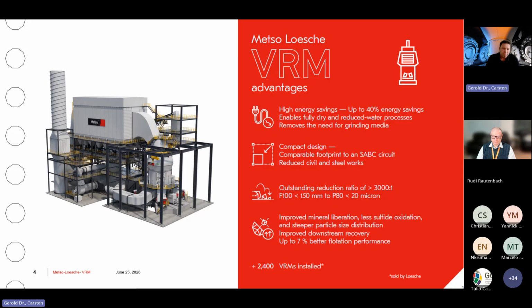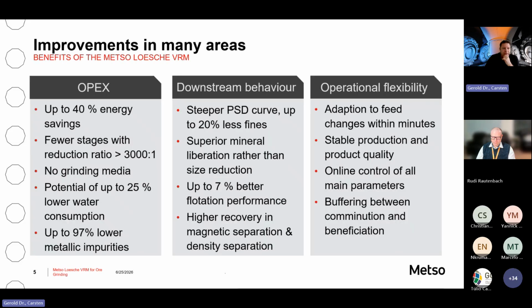What we see through the compressive grinding that we do is improved mineral liberation, less sulfide oxidation, steeper particle size distributions, improved downstream recovery, and up to 7% better flotation performance. Up to now, we have installed more than 2,400 VRMs. And there are different points we will touch on today.